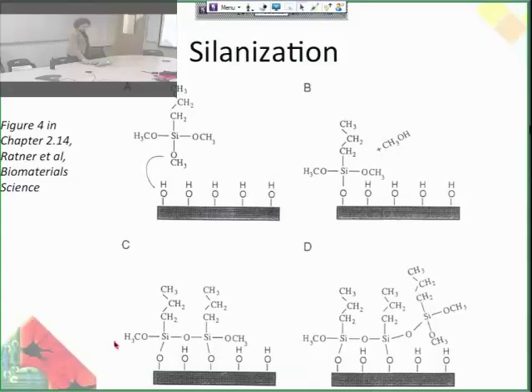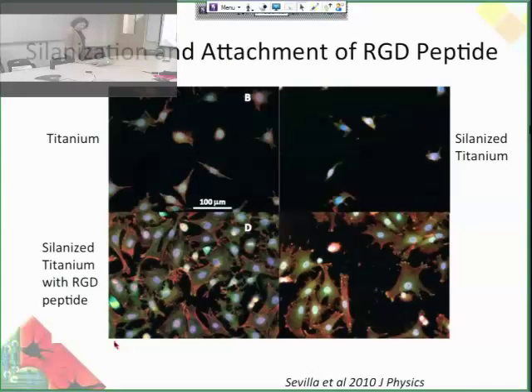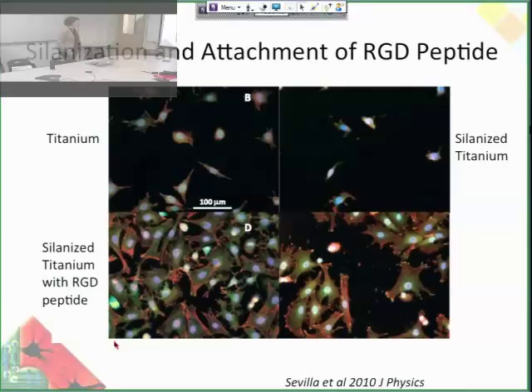This is an example of how silanization was used to attach the RGD peptide — arginine-glycine-aspartate — which is one of the most famous peptides studied for cell adhesion. It's isolated from fibronectin; that's why fibronectin is adhesive, because of the RGD sequence. So on titanium with not much cell attachment (osteoblasts), when you silanize it, it becomes really hydrophobic and there's even less cell attachment. But if you silanize it and then add the RGD peptide using this technique, you now get a lot of cell attachment.